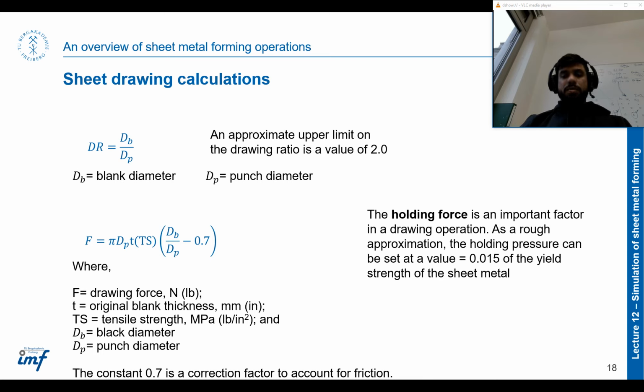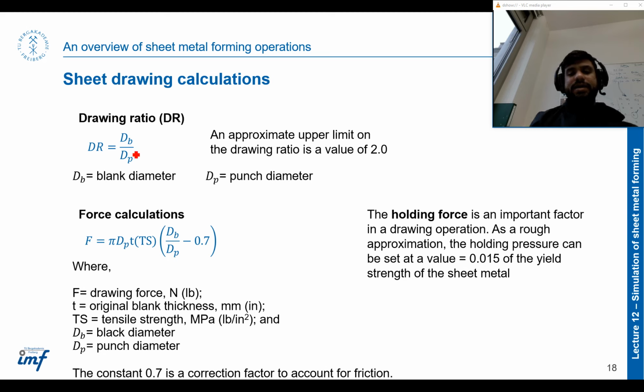draw ratio. So we can calculate that easily by dividing the blank diameter by the punch diameter, and then we get a draw ratio. It is important to understand that the upper limit of the draw ratio is 2.0, which means that if the diameter of the blank is more than two times the diameter of the punch, it will be quite hard to draw it inwards. It will cause earing on the outer edges. It will cause tearing in the wall because the tension in the wall will not be able to pull the material through the die. And there are many things that take place, but yeah, it is important to understand.